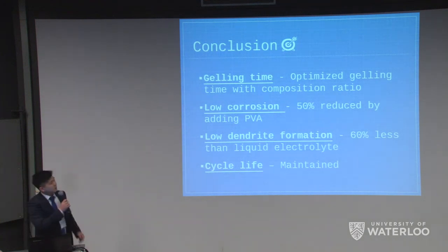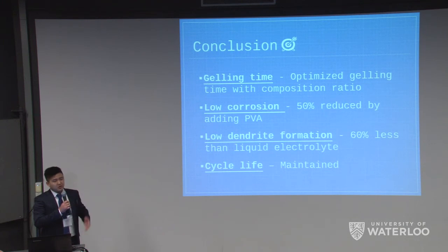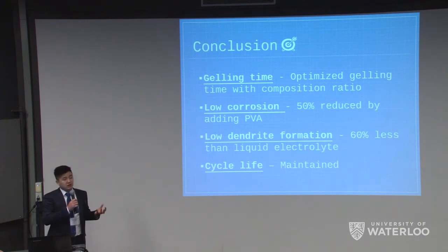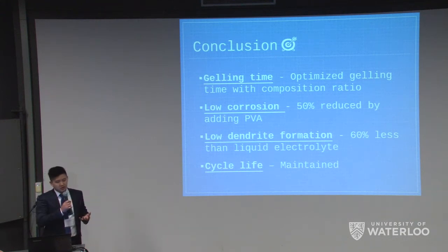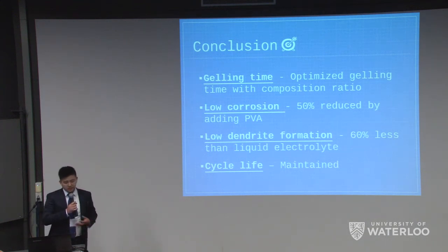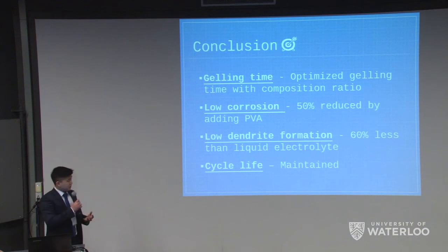So in conclusion, we controlled the ratio of the components in the additive, and we could optimize the gelling time that's required for the industry. And also we greatly reduced the corrosion and dendritic formation compared to the liquid electrolyte. And also the cycle life performance was maintained.